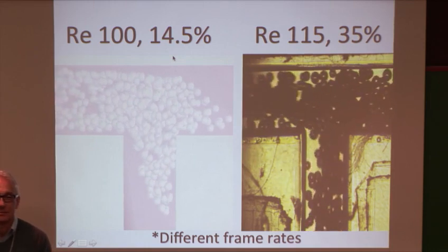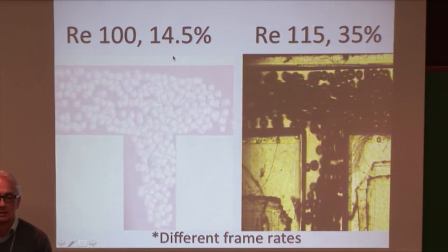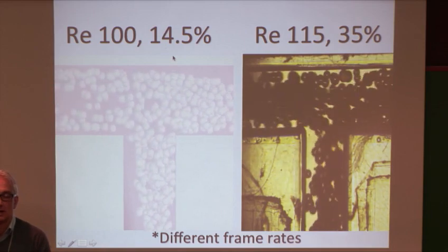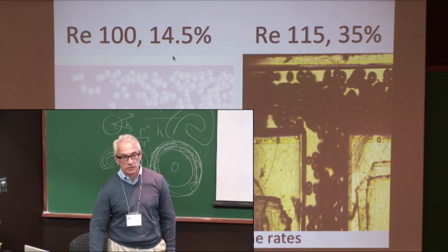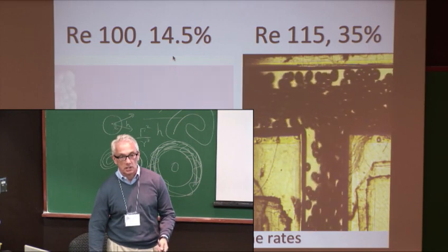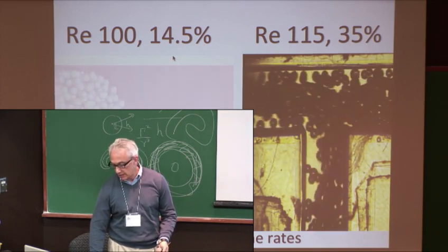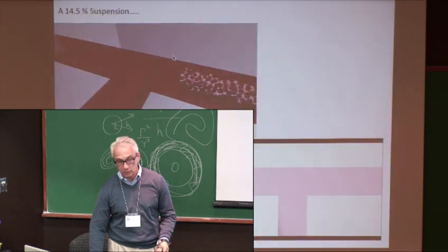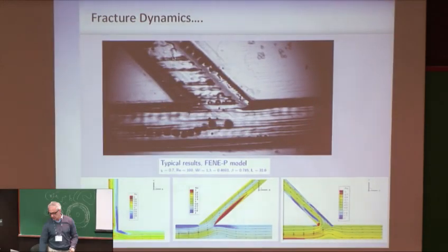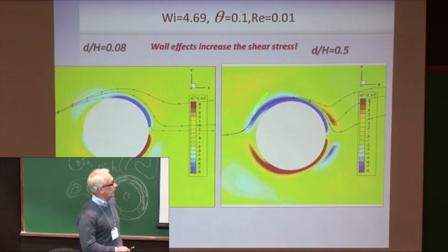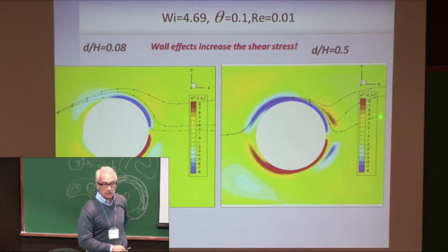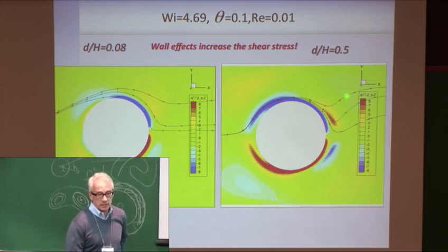You found these big wings. So what can you say in general, get more and more particles? So that means, actually, the single particle one is only valid for very dilute. Yes. That's actually correct. And I think that's why there's such a big effect with concentration. How do the wings interact with each other? This is what I hope. I hope they interact like the walls interact with. In one sense, we were happy that the walls enhance the effect because we also know, for example, here, what's happening is the wings are interacting with the walls. You're ending up getting an increase in stress. You get some interaction with the wall. Now, remember here, most of the stretch is in this direction. But there is some angle to those wings. So these wings will interact with the wall. If you look at the structures that sedimenting particles make in viscoelastic fluids, they actually follow each other. There's trains in the gravity direction. If orthogonal shear is in the perpendicular direction, then in some sense, the other particles are acting like walls. They're not quite in the shear direction, but they're above and below. So that's what our hope is. Particle interactions are like particle-wall interactions in some sense. We're getting more bending of streamlines around each individual particle. It's very clear that dilute, in this case, is single ball bearings.